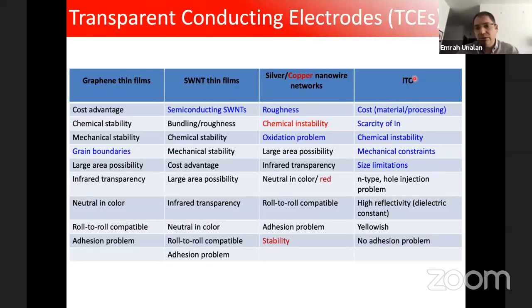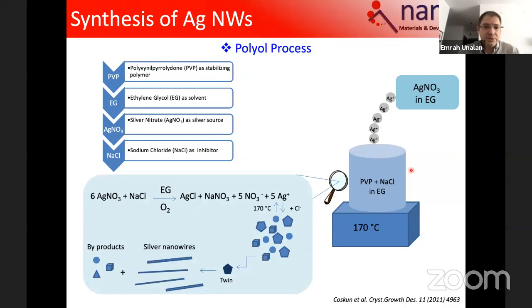In contrast, on the ITO, cost, that is both due to the scarcity of indium and the processing. So high performance ITO is still sputter deposited. Chemical instability. It's an oxide material, so you might need to take care of the chemical instability. Mechanical constraints. I talked about that. And since we say that it is sputter deposited, for sure roll-to-roll sputtering processes are out there, but it's not a cheap process to roll-to-roll deposit this thin film, so size limitations arise if you deal with the ITO.